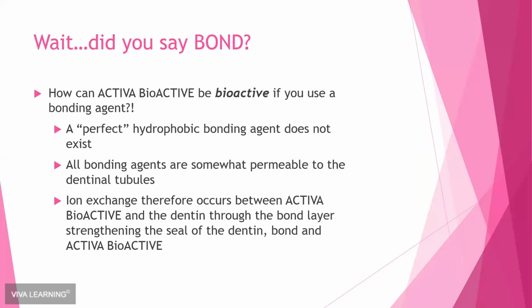So I want to talk about bonding, because in the previous slide, when we were showing the bond strength of the material and the micro leakage, we presented that without any sort of bond being used. So the question that comes up is, if you bond with Activa Bioactive, are you going to interfere with the material's ability to bond to the tooth structure? And the answer is no. And the reason that that still works, that you can still get this apatite formation and this mechanical bond with the tooth, is that a perfect hydrophobic bonding agent doesn't exist, probably despite all the manufacturers' best efforts.